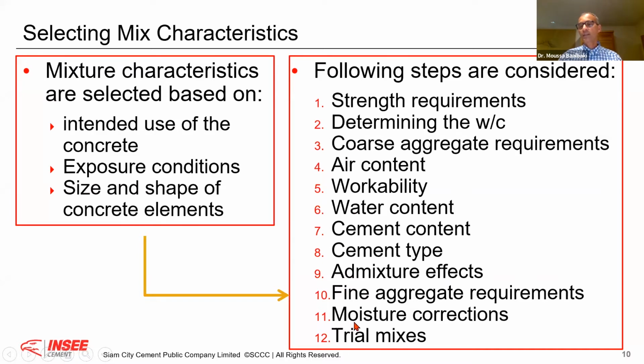Why do I say moisture correction? Because if you go to the job site and look at sand or aggregate on the piles, very often they are not in what we call saturated surface dry. Therefore, they are wet or they are too dry. Therefore, you need to do a moisture correction to assure that you always have a mix design with the same water cement ratio. Otherwise, if I do not consider the moisture correction, and for example I have 800 kilograms per cubic meter of sand, and I make a mistake of 1% with my moisture because it was raining yesterday, suddenly I will bring 8 liters of water more into my mix. You see, this has a very big impact on the properties of the concrete afterwards, before you go to the dry mix.